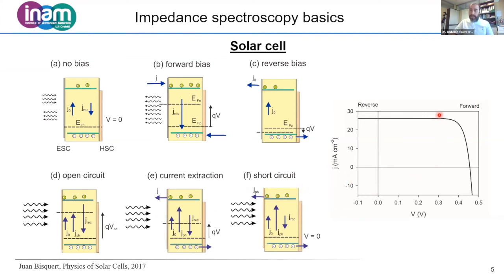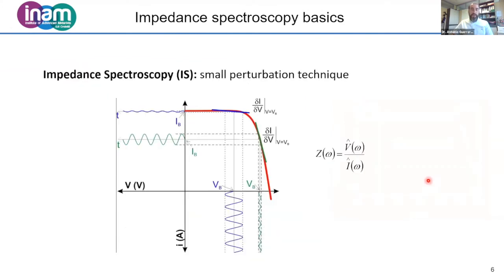Okay, so starting from this JV curve, we do impedance spectroscopy, which is a small perturbation technique. In this technique, we can place ourselves wherever we want in the JV curve by applying a direct current voltage, a DC voltage. For example, here we can apply a voltage, and over this DC voltage, we apply a small AC perturbation. This is the input that we introduce into our system, and the solar cell will operate, and we will be able to measure some current. This is the output current that we are able to measure.